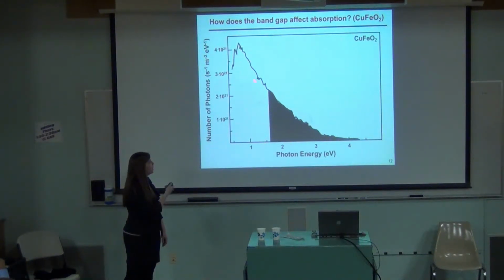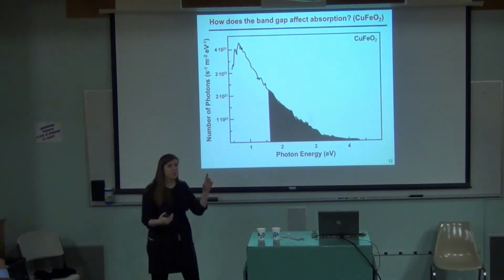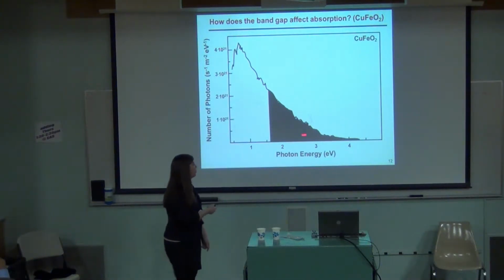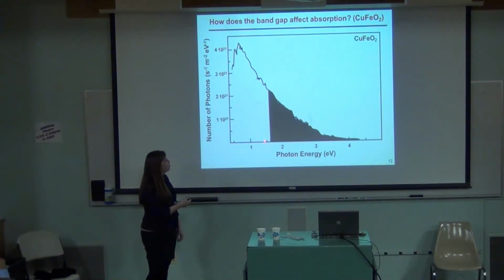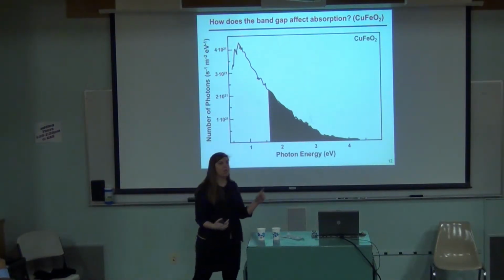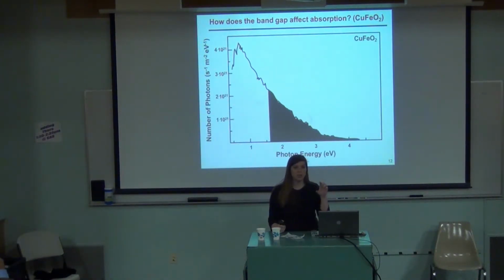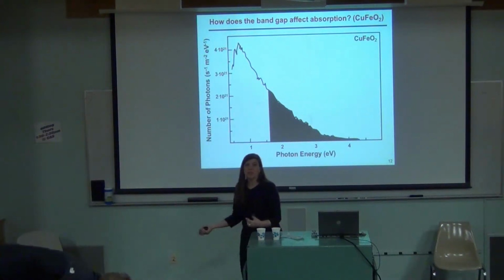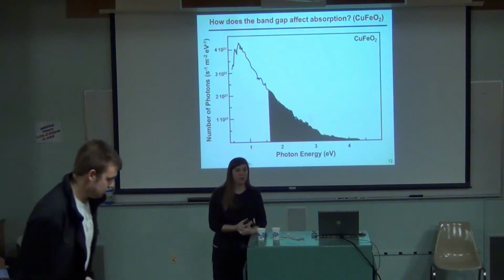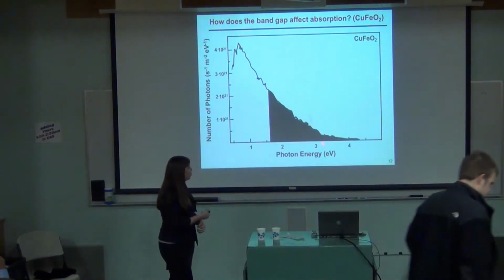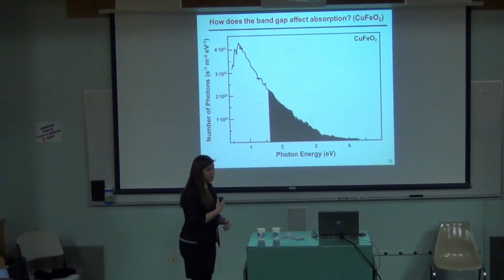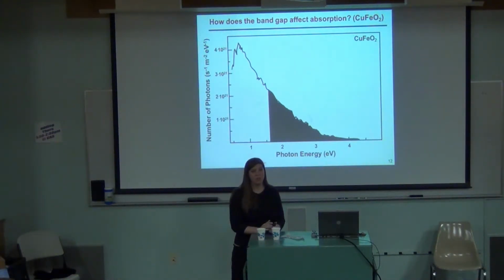And really, this portion is unusable because of the band position. So we're about at the max efficiency when we're here, because you need 1.23 eV as the split between the hydrogen position and the oxygen position. So you can't really be any smaller than that, which means that if we're using all of this, that's the best we can do. We can't do any better than that. So this, in a way, is the most efficient material you could make. It needs some more studying to be a more efficient material on its own, but it does have the capability of being a great material.